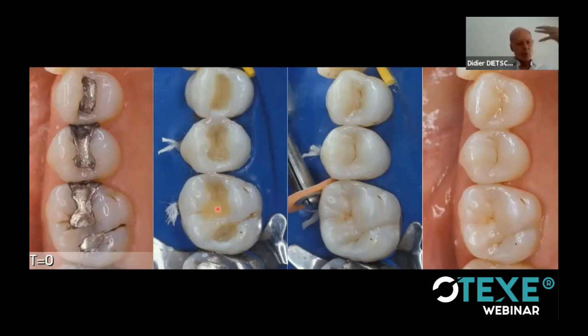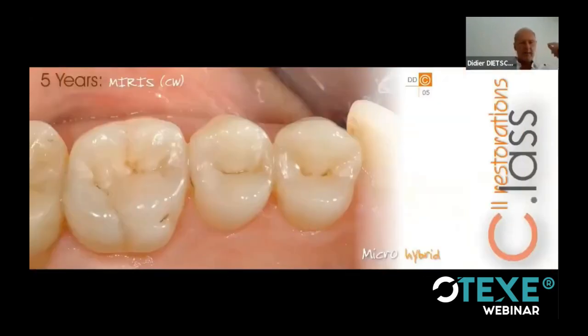You see here the same protocol you have seen already briefly before. We use dentin to replace the dentin, enamel-like material to replace the enamel. And you see the final situation after changing those small amalgams. We are 5 years down the road. That was done with the Miris, which is a conventional microhybrid. And you see after 5 years that we have no visible change, no visible aging or degradation of the margins.